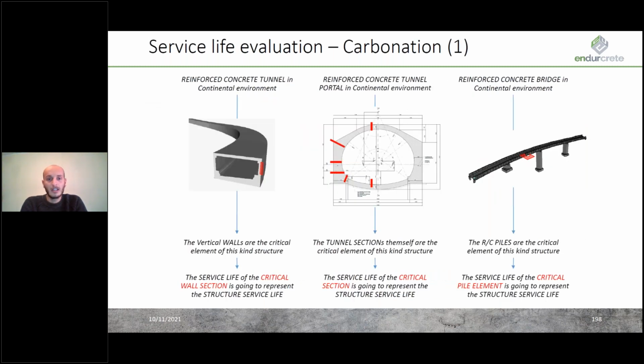The second phenomenon analyzed is carbonation. This phenomenon is assessed in 3 different structures. The first 2 are 2 different concrete tunnels in a continental environment, and the third one is a reinforced concrete bridge in a continental environment. Also in this case, for the first 2 structures, we check for the critical section in the lining of the tunnel, while in the third one, we check for the critical pile element among the 3 different piles in the structure.